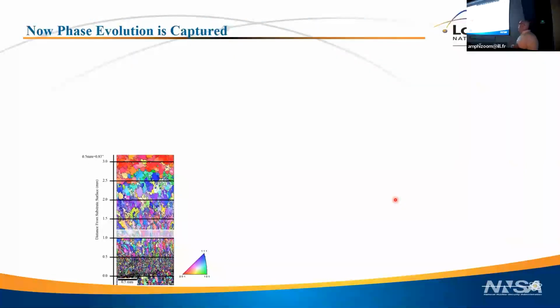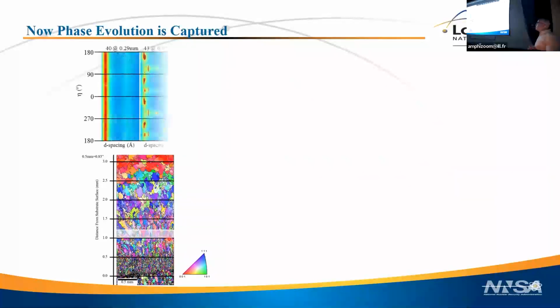So we make one of these and we cut it, and that's what the microstructure looks like when it's all said and done. This is what you'd expect for AM, very close to the substrate. You get very small grains because the solidification rate is high down here. And as you go up, they turn into columnar grains. This is, for the data I'm going to show you, this is where the X-ray beam penetrates. So we're integrating all of the diffraction from this part of the microstructure.